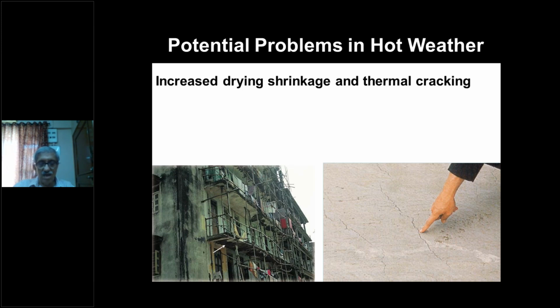Now, plastic shrinkage occurs when concrete is still plastic. Drying shrinkage occurs after concrete has hardened. And if the curing is not done properly, or there are several other reasons, the concrete starts cracking and the cracks become wider and wider after the concrete has hardened. And then what happens? It allows the moisture and the chemicals from outside to go into the concrete. Corrosion happens. When corrosion happens, the bars, due to the rust formation, increase in volume. They give tremendous tension within the concrete and the concrete starts cracking.